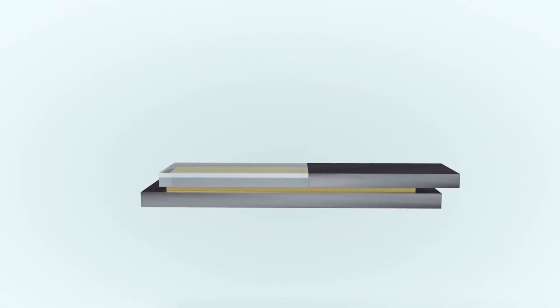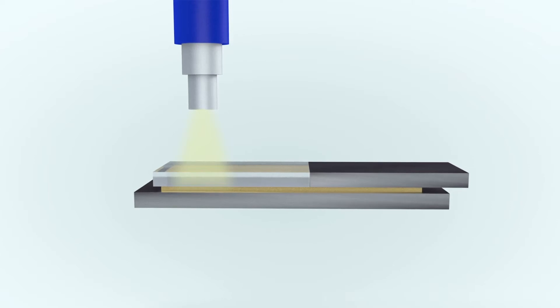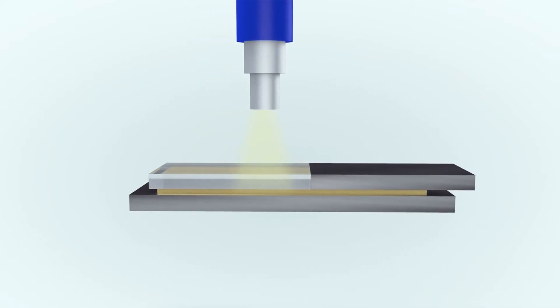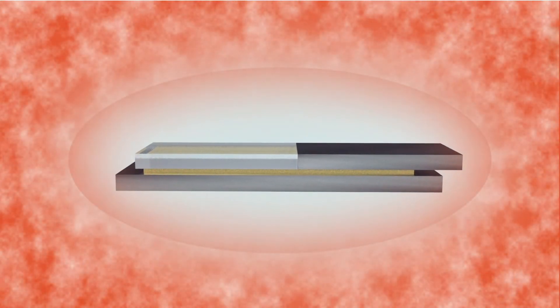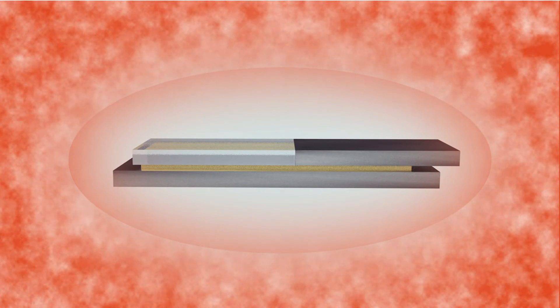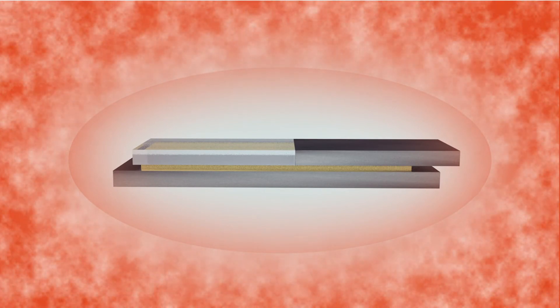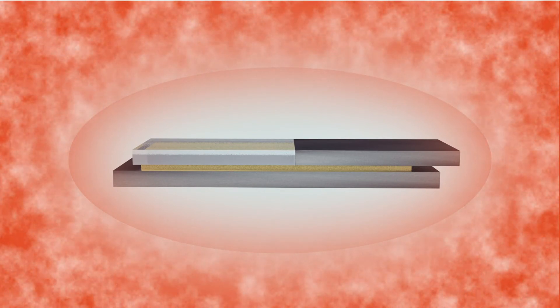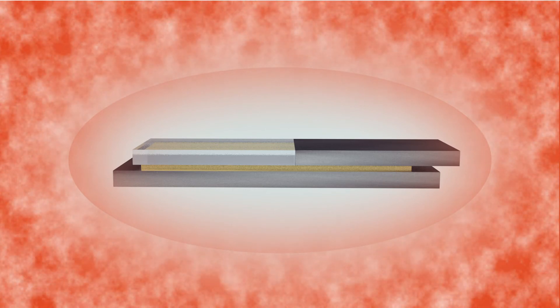The UV cured sections cure in just a few seconds when exposed to a UV light source, while the heat cures are typically initiated at temperatures as low as 80 degrees Celsius, 176 degrees Fahrenheit, and cure in about 20 to 30 minutes.